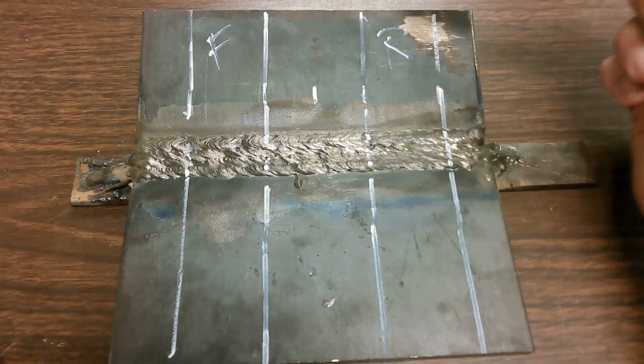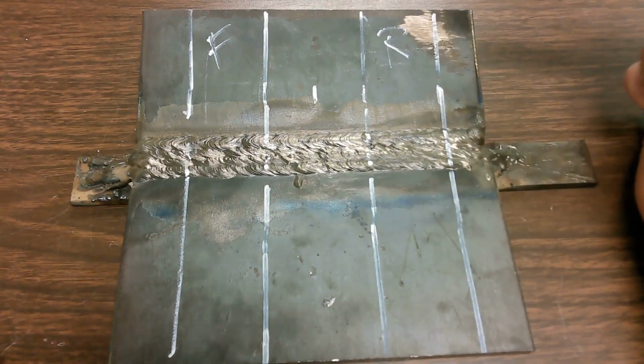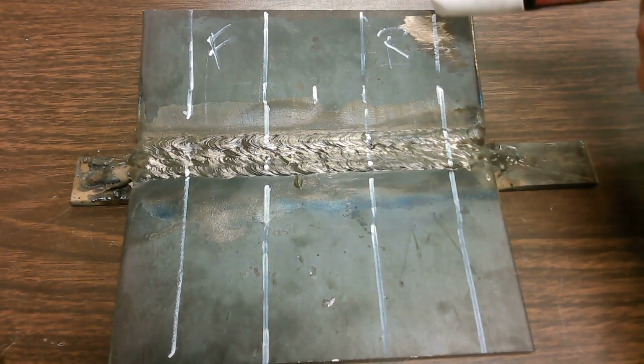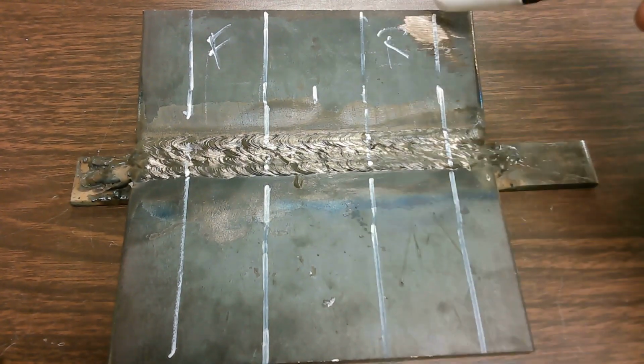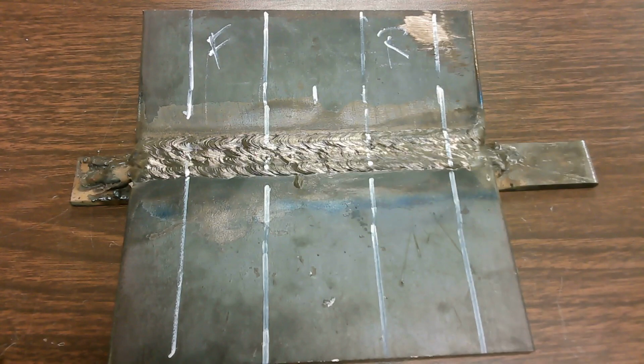Okay, so we've got everything marked out. A few different ways we can cut this. We could cut it with a torch. We could cut it with a plasma cutter, whether it's on a track system or handheld. If you're doing handheld, torch, or plasma, I'd recommend a straight edge of some kind so you can keep those edges nice and straight. It's probably faster than saw cutting, but it's not as accurate, and they're typically a little bit more cleanup.